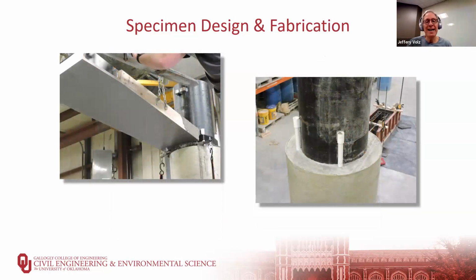So this is one of the SCC columns with the concrete being placed with a chute that we fabricated to lower the concrete from our concrete bucket into that annular space. This is a self-consolidating concrete. It flowed very well. It had about a 26 to 28 inch spread. It consisted of 3/8 inch maximum aggregate because of the only 2 3/4 inch thickness of the concrete. We didn't want to use a larger aggregate. And it flowed very well with no external vibration or internal vibration, and filled up that annular space extremely well.